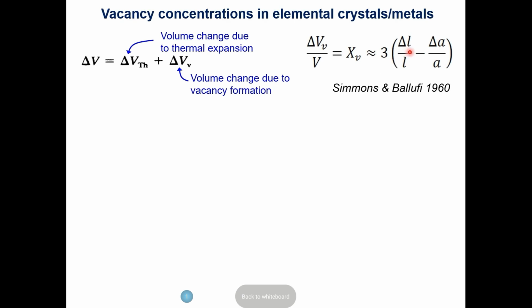This can be easily measured. People use for fancy measurement a dilatometer, so depending on how fancy it is, you can measure very minuscule changes in dimension. There are techniques to measure dimensional change, and then you normalize by the original length. That's easy. But how can we measure this change in lattice parameter?